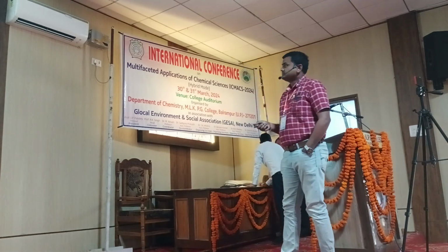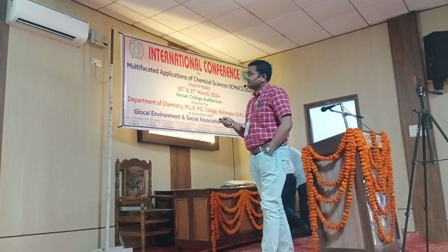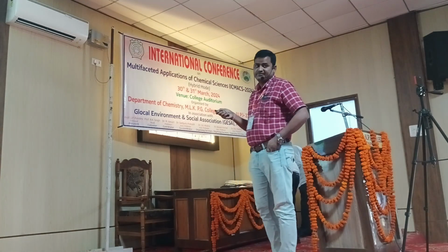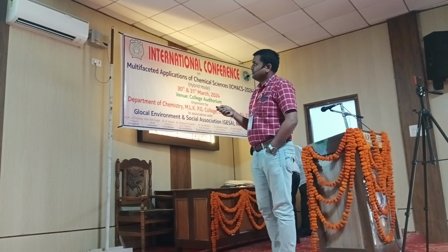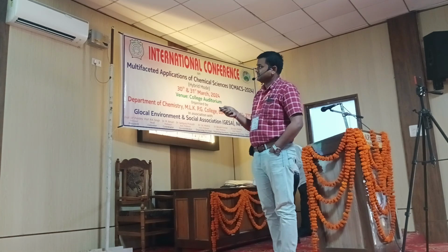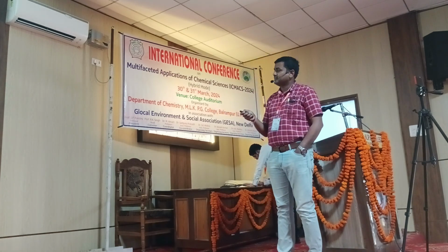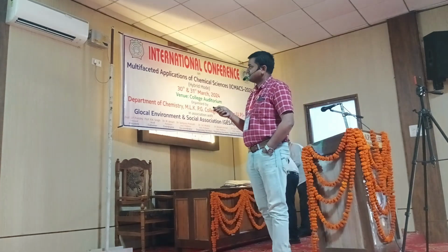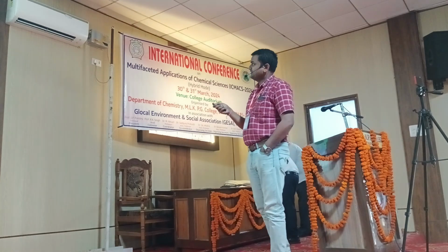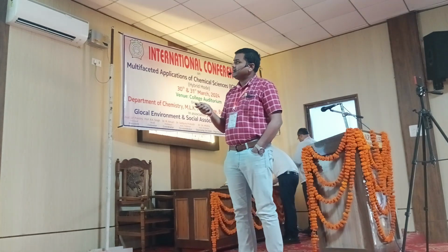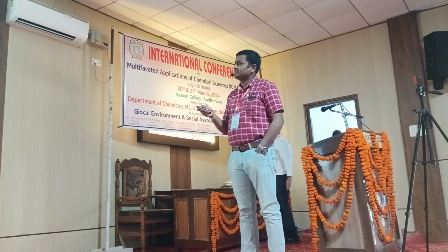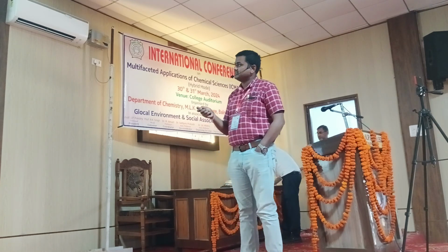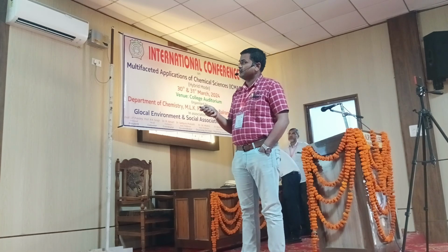Next, we mixed this white light emitting solution with a PVA polymer matrix. After mixing this graphene quantum dot in PVA solution, we found perfect white light emission under UV light excitation. The quantum yield is 0.52, which is good enough compared with other reported methods, and the CIE values are 0.28 and 0.30.